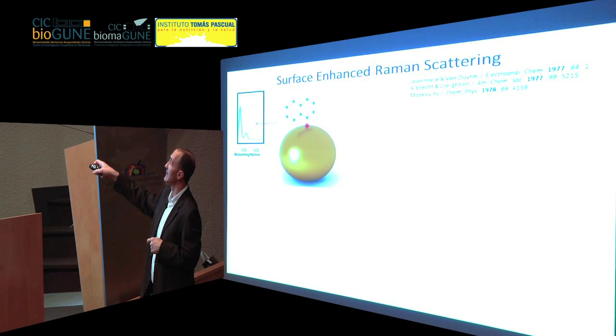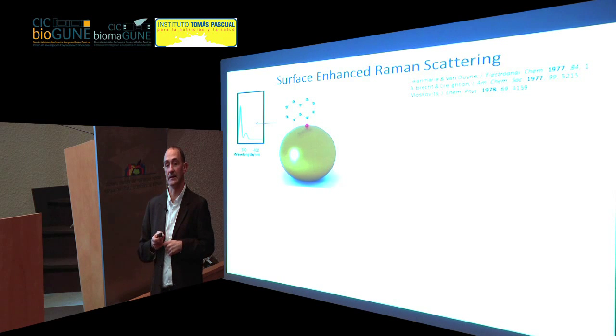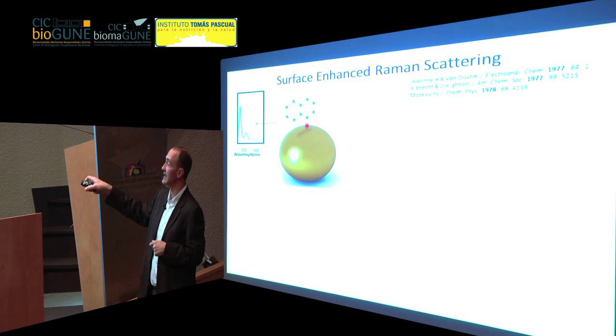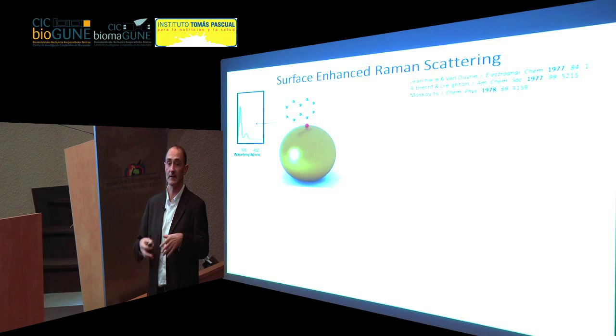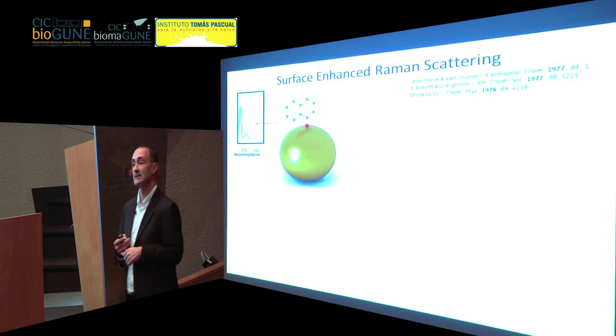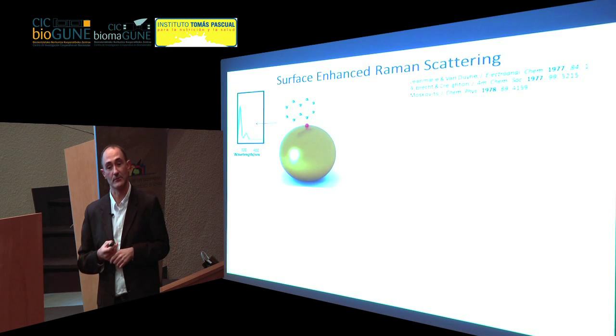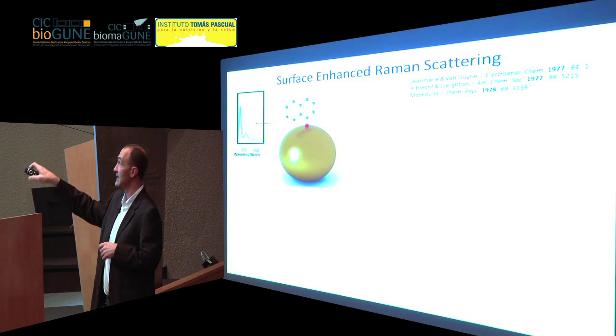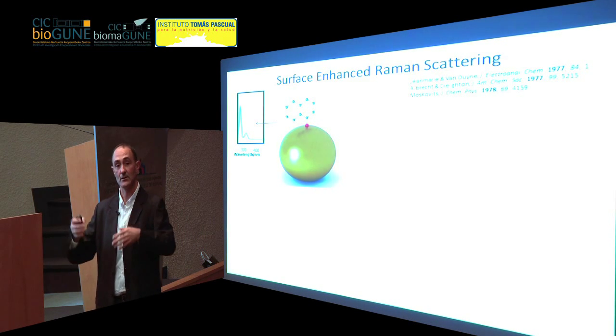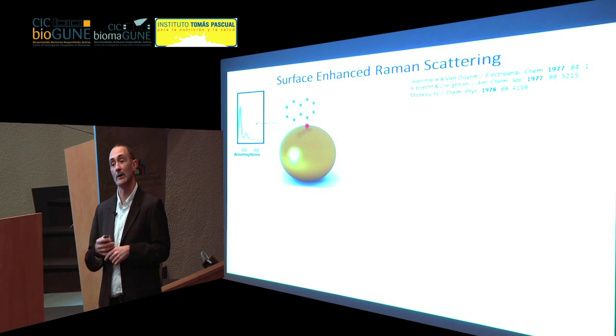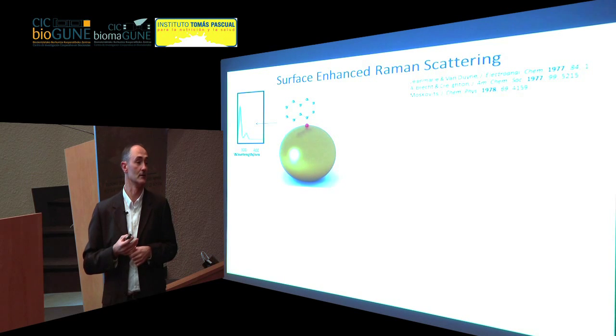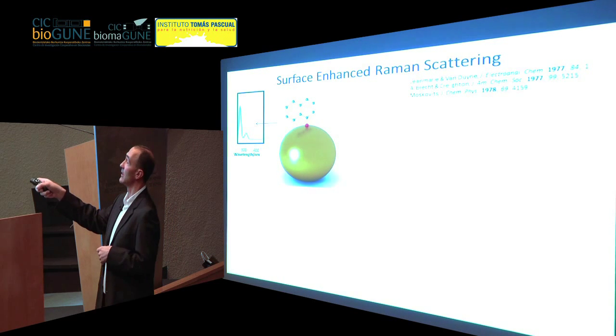So these people here came and tried to explain that actually what happened is that when you're exciting the silver electrode, which is very rough indeed, you have many nanometer scale grains, so you're actually exciting surface plasmon resonances in these grains, and then you're creating a high electric field which affects the polarizability of the molecules, and this is why you get this high enhancement of the Raman signal. So you could think of implementing this.